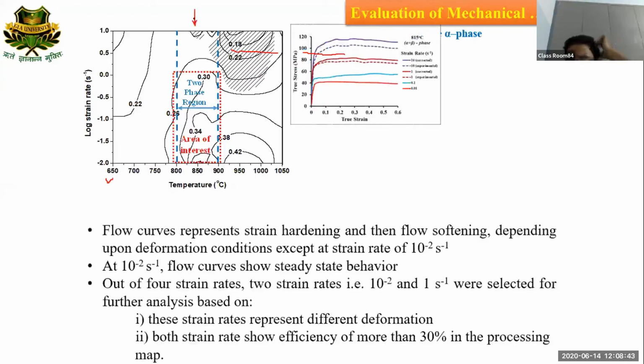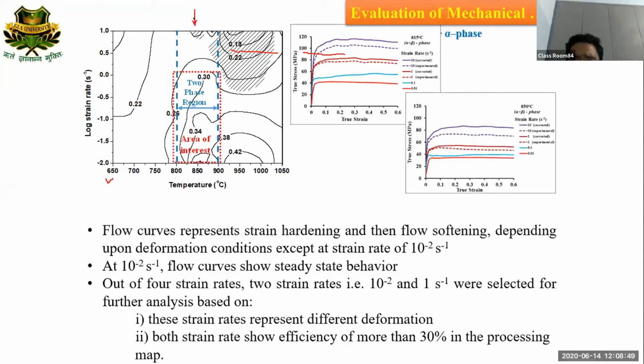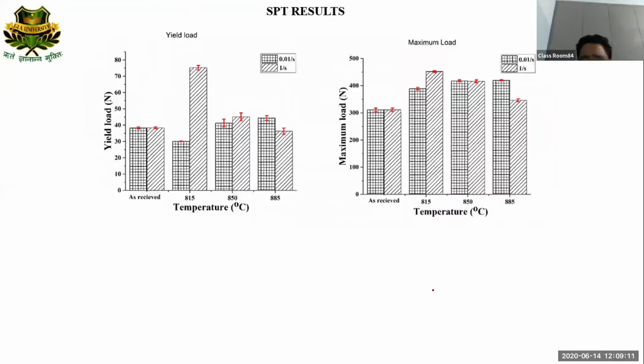Here on the right side you can see some flow curves. From the flow curves I have chosen some specific conditions where I have seen some distinguished features. Here I have taken only two conditions, one is 10 to the power minus 2 and the other 1 strain rate, for a particular temperature zone. Further, from the deformed sample I have taken a very small disc, around 0.26 mm. That kind of disc we have prepared and conducted the small punch test.